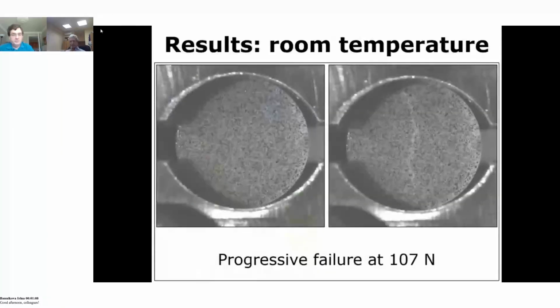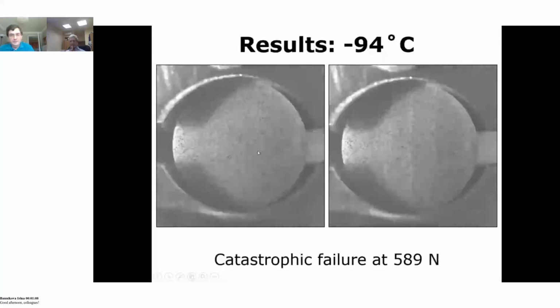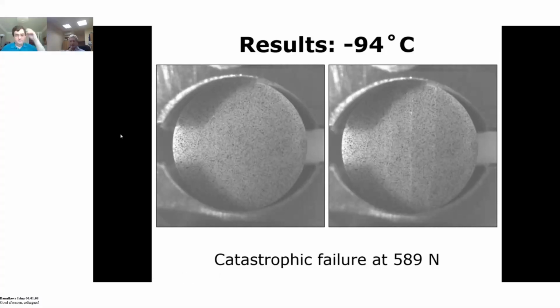So these are the results at room temperature. Basically, what we have on the left-hand side here is the initial sample, and there was progressive failure at around 107 newtons applied force in the system. So that was the results at room temperature. When we looked at -94, this is the sample there, and there you can see some cracks which appeared suddenly, so catastrophically, at 589 newtons.